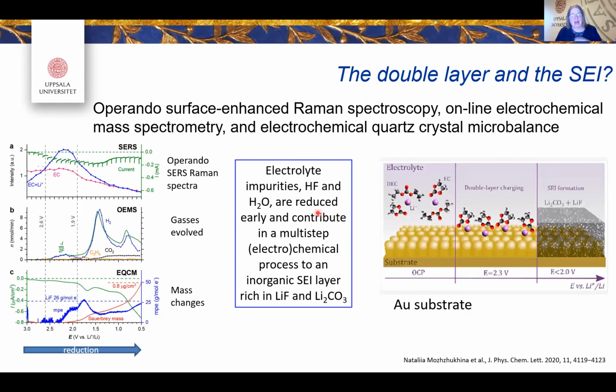One more thing when it comes to handling the SEI has to do with the gassing. I've already indicated that you can have gas, especially if you have exfoliation. And here's a model study we did, not using graphite, but a gold substrate, with the typical electrolytes that you have in the battery. We did operando surface enhanced Raman spectroscopy, online electrochemical mass spectrometry, and electrochemical quartz crystal microbalance. It's my co-worker Erik Berg who's working on this. And if you look at these graphs where we go from the reduction, which means inserting lithium more into the gold,